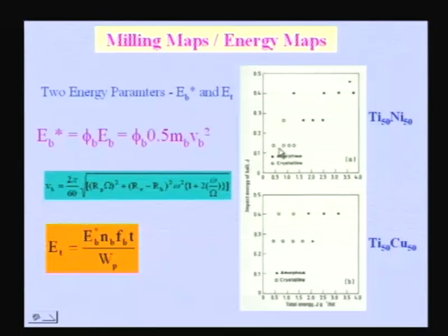You see that irrespective of the impact energy, there are 3 or 4 different levels of impact energies here, and at each impact energy the total energy is increasing in this direction, and you can see that there is a critical value of total energy beyond which the amorphous phase forms. Below that it does not form.